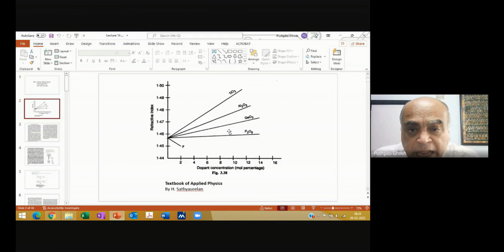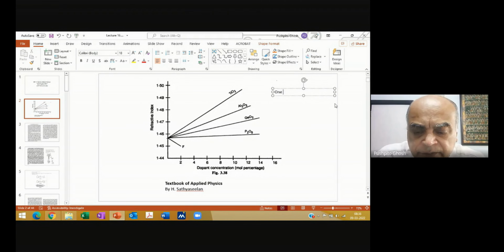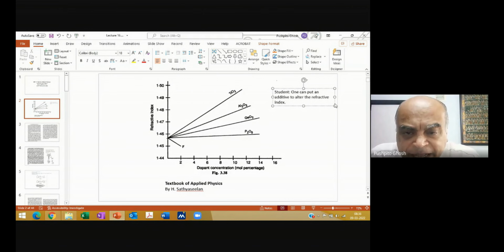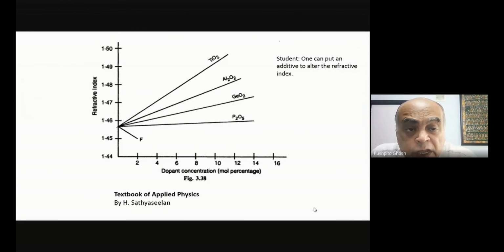Okay. Good. So one can put an additive to alter the refractive index. And that's precisely what you see in this plot. Suppose I take silica, pure silica, which is quartz, and then I add different types of additives into it.